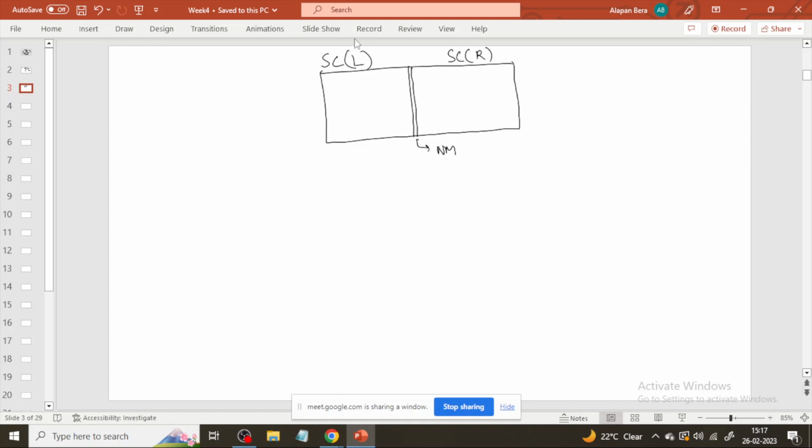Now let's say the wave function of the Cooper pairs appearing here is given by this. As you know from the last interactive session or the week 3 lectures, the electrons in a superconducting sample are phase locked, and that can be expressed by this macroscopic equation, where the phase of all electrons is given by delta 1, and the amplitude of the wave function is psi naught. Okay, and the density of the superconducting Cooper pairs is given by psi star psi, which is equal to mod psi squared.